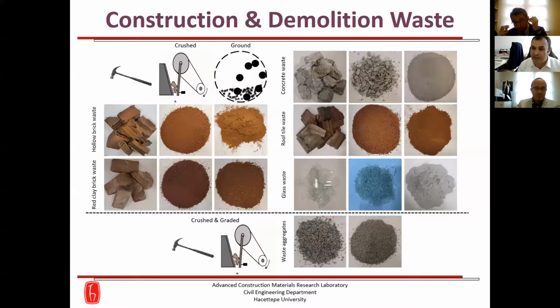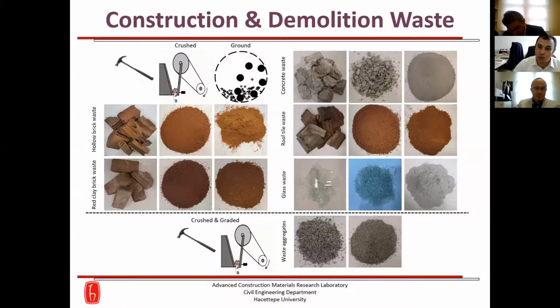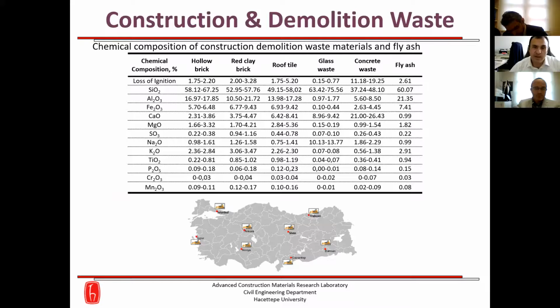We do not need any additional procedures to obtain the concrete waste as a powder or as aggregate particles. And you can see the chemical composition of the construction demolition waste in this table, which are obtained from different parts of Turkey: Istanbul, Izmir, Konya, Ankara, Sivas, Trabzon, Batman, Gaziantep. And at the end of the table, you can see the chemical composition of the fly ash, which is commonly used in the production of concrete.